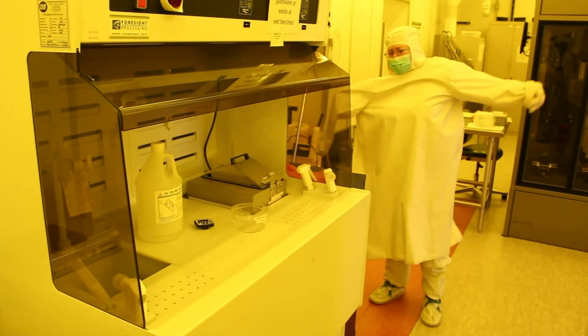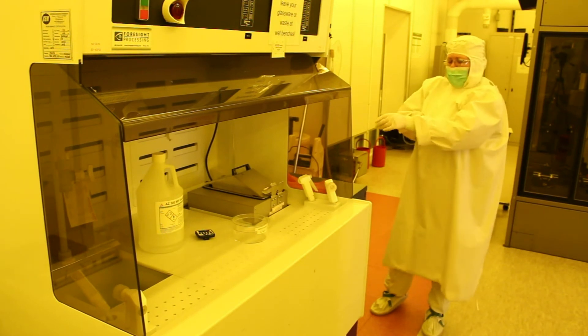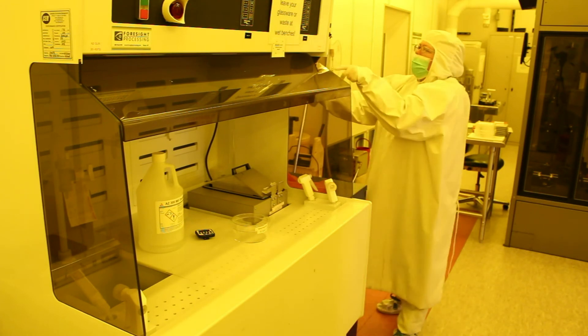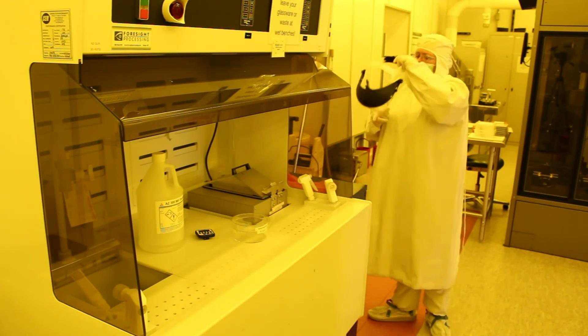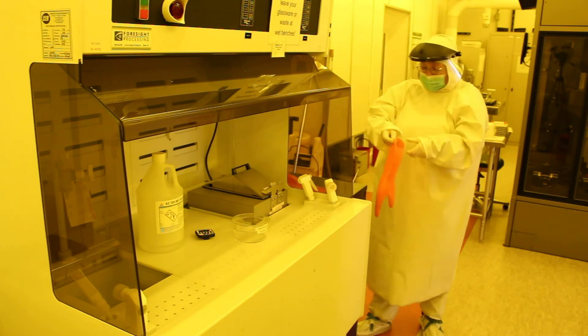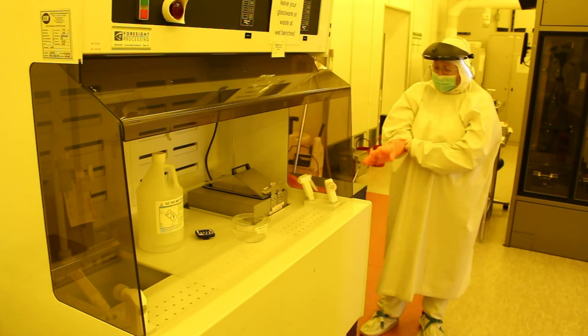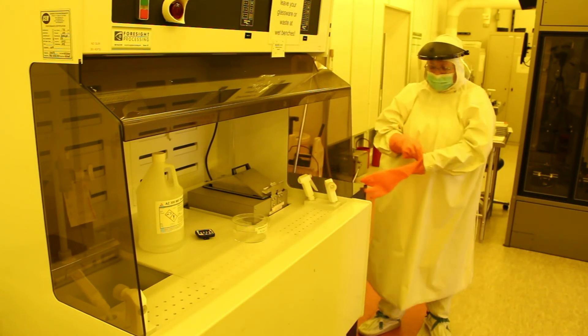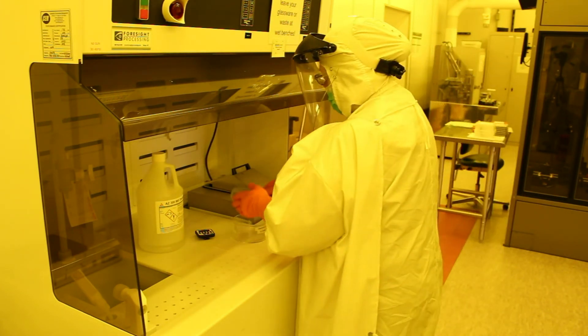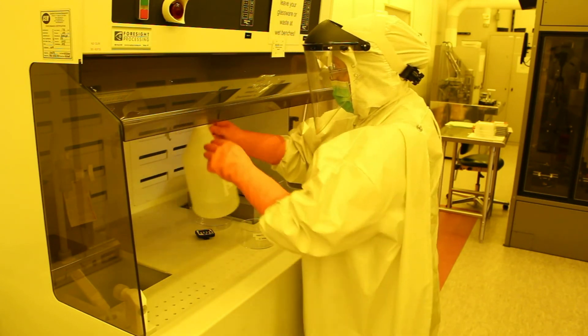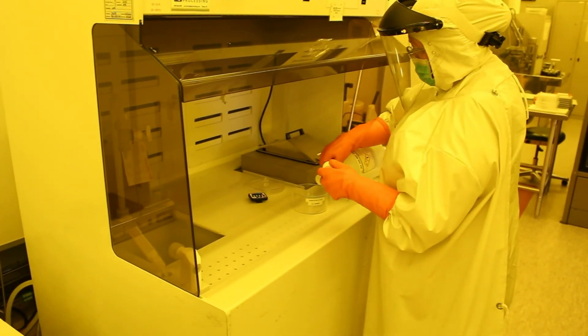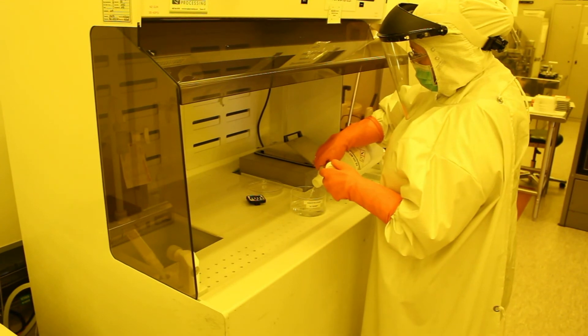Developing the resist is done in a base hood because the developer is a mild base solution, usually TMAH, some surfactants in water. It's usually a very low percentage, usually in the 2 to 2.5% TMAH concentration. Because TMAH is used in the developer, full PPE must be used because TMAH is a nerve degenerative agent. So anytime handling the fresh solution or the waste, full PPE must be used. The developer is dispensed into a beaker just enough to be able to immerse the wafer with a reasonable amount of bulk material to absorb the resist and not get oversaturated.